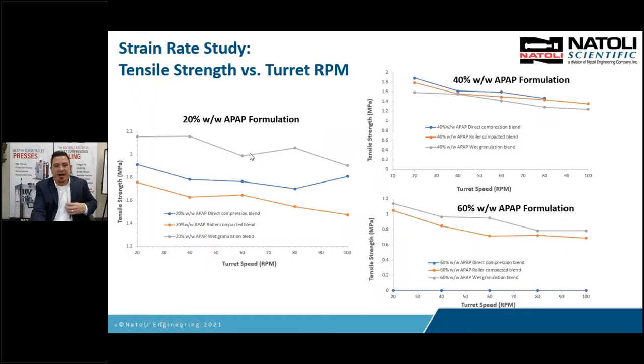All right. Now let's talk about the strain rate sensitivity studies. So for the tabletability, we kept the turret speed and weight constant, and we increased our pressure, and we collected samples at each pressure. For the strain rate, we want to keep our compaction pressure constant, and we want to start at a slow turret speed and collect tablets. Increase speed, collect tablets, all the way up to max speed. And you'll notice on our RD30, we were able to run up to 100 RPM.